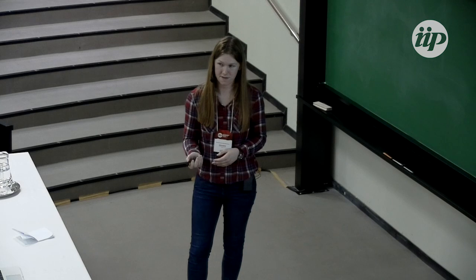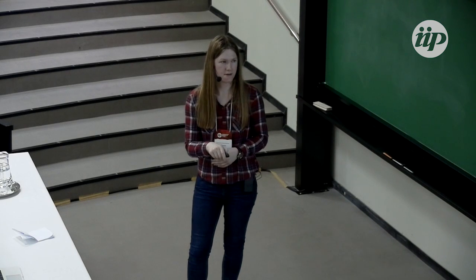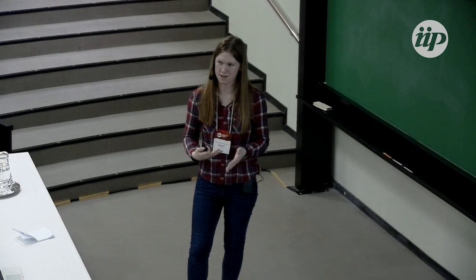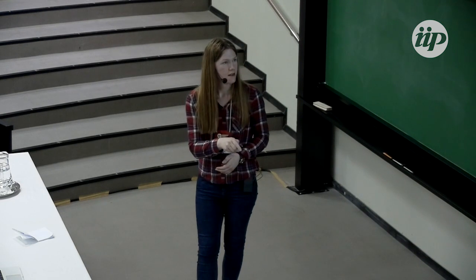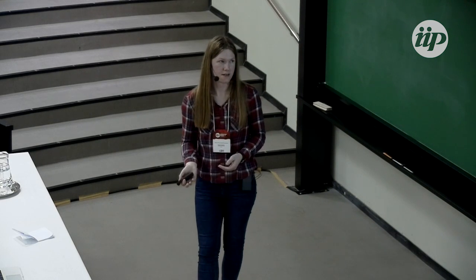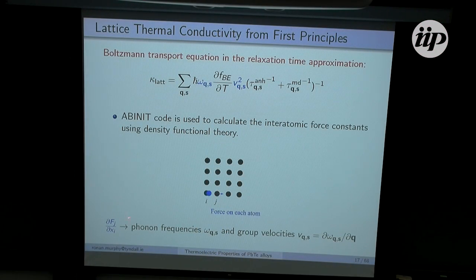So we use a finite difference supercell approach. This will probably seem a little bit familiar, but we use the Phono3py code to generate our supercells and to then generate atomic displacements within them. Now, we then pass these displacements to Abinit, and using DFT, we calculate the interatomic force constants. Now, from the first order derivative of the forces with respect to atomic displacement, or you can say imagine displacing 1 atom and calculating the forces on all the other atoms due to this displacement, you get the phonon frequencies omega and the group velocities v. And from the second order derivative of the forces with respect to atomic displacement, you can get the anharmonic phonon lifetimes tau, and then plugging it back into the formula here, we can get the lattice thermal conductivity.